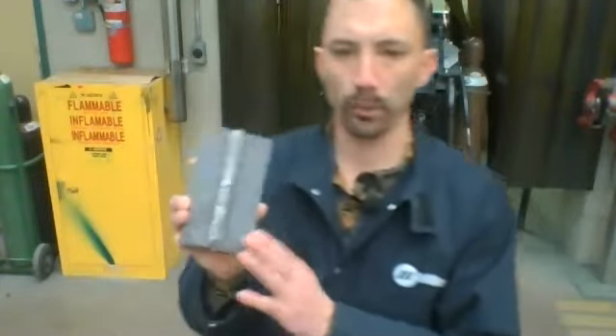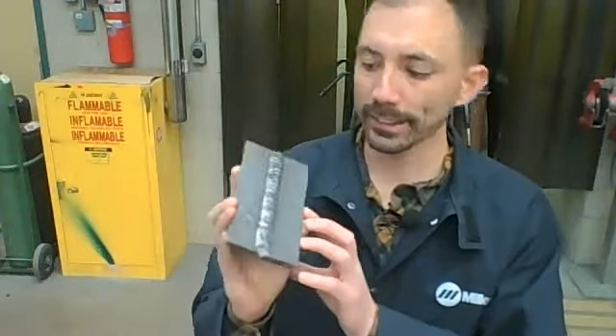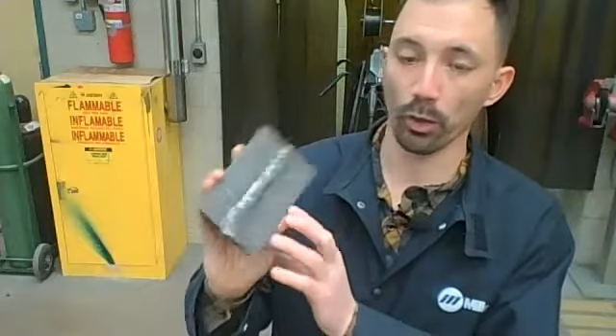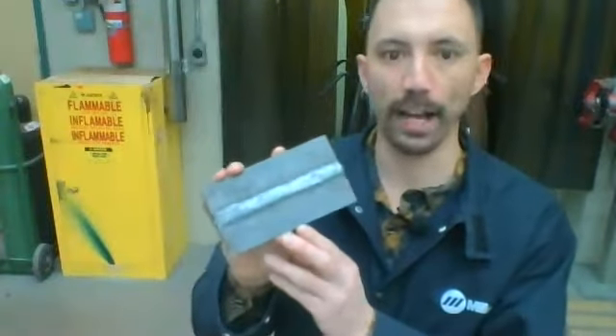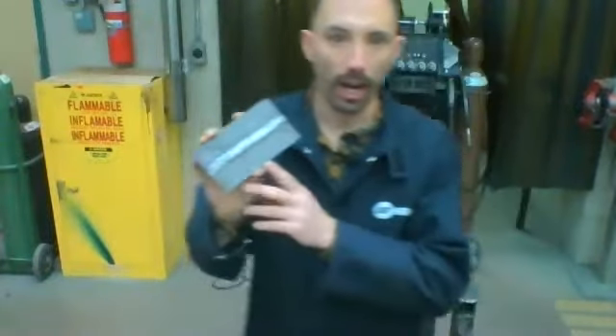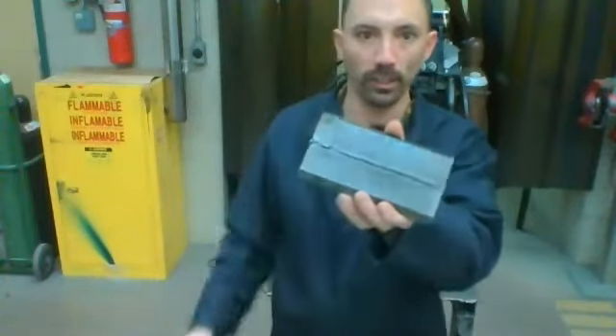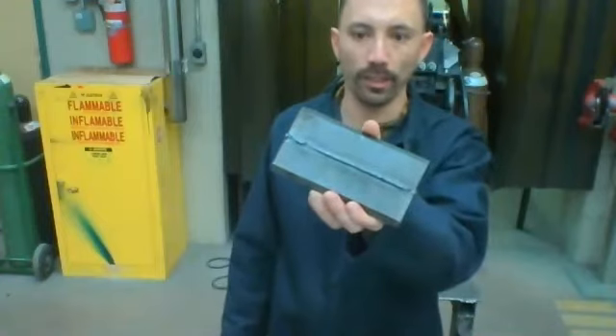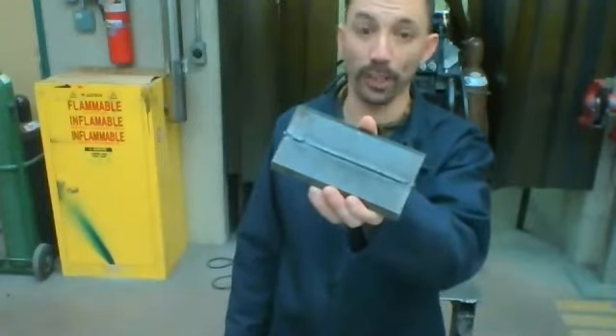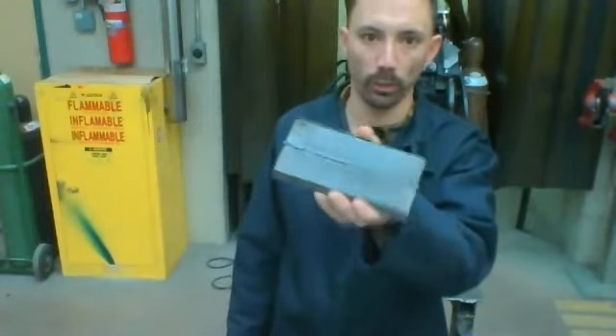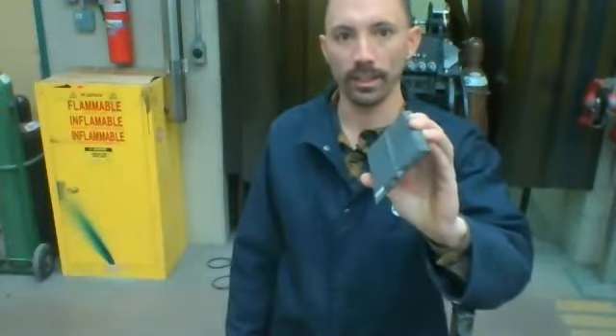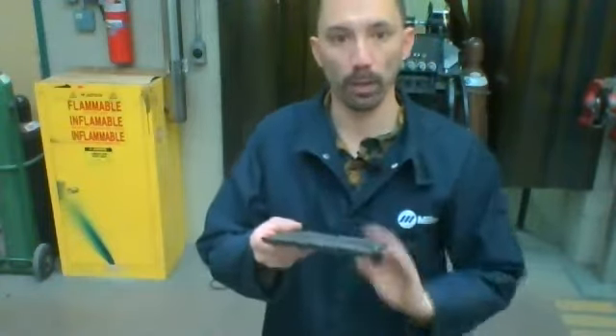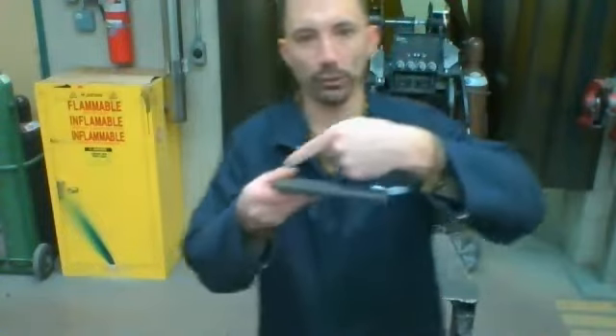All right, so what we have here is that flux core 1G. So this was the flat groove that we worked on. With this, we put the root in right down there. We put that root in with 70S-6 solid wire, so gas metal arc welding solid wire for that root. Then we did the fill and the cap all full of flux core. And it was a backhand drag.